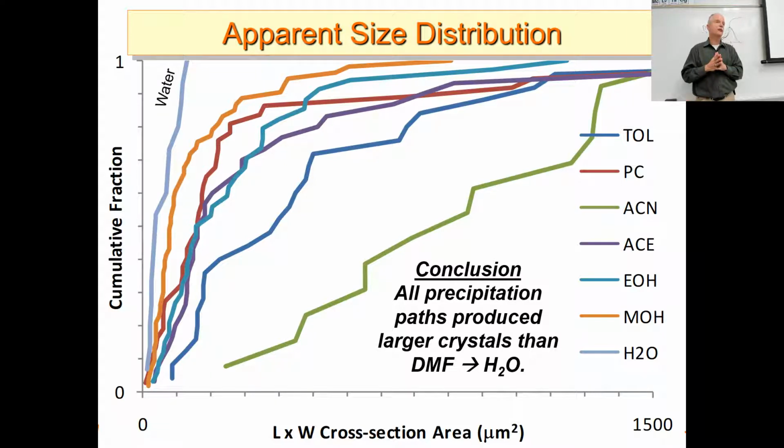And that's what you do in the back of the hood, which I don't even like using because it vibrates. You put your reactants, your products, in non-solvents in a test tube rack, covered with parafilm, which is a bit porous, and set it in a dark corner of the lab and go away. And then you get really big crystals. That's the best way to crystallize something: put it in a slight non-solvent and let it grow slowly. Those you can pick and put in an X-ray crystallographic machine.